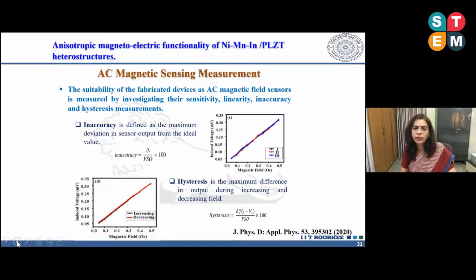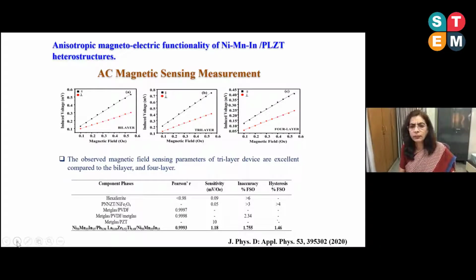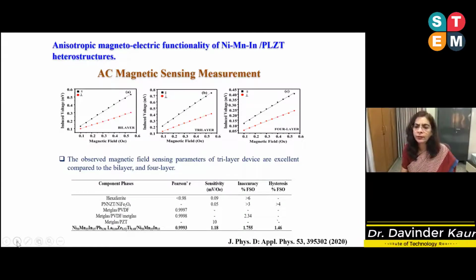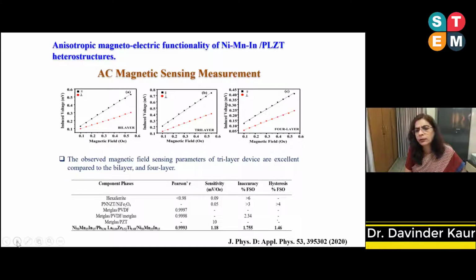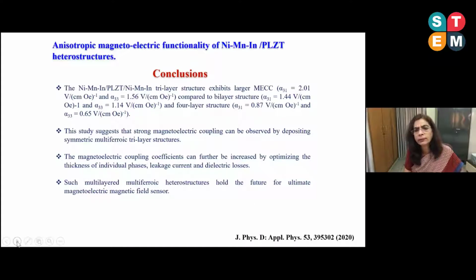Next please. Hysteresis and inaccuracy were calculated using these formulas, and these are the reported values. The Pearson coefficient is 0.9993, sensitivity comes out to be 1.18, inaccuracy 1.755, and hysteresis 1.46. This has been compared with literature values, and the results were okay, quite promising.